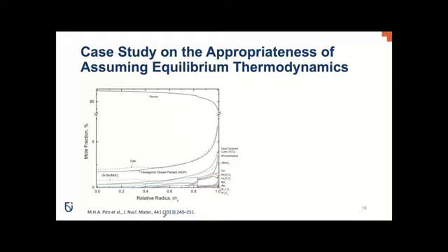So what you're looking at on slide 19 is an analysis I performed about a decade ago in high burn-up PWR fuel. And what you're looking at on the left figure is the predicted distribution of phases across the radial direction at end of life in very high burnup PWR fuel. It's about 100 gigawatt days per ton fuel. It's pretty high burnup.